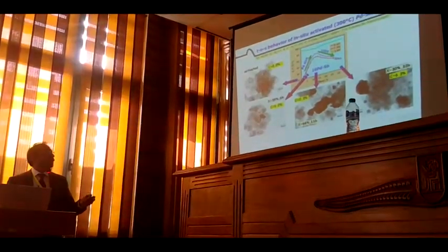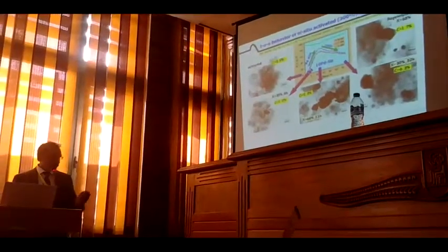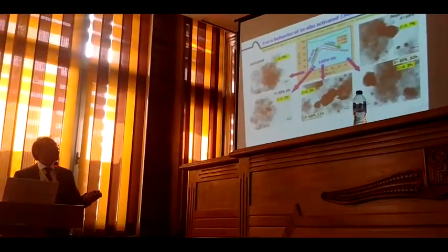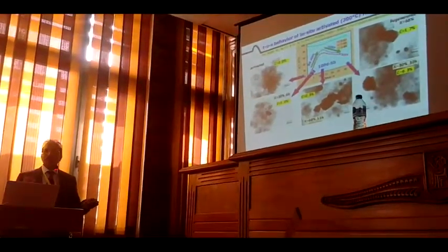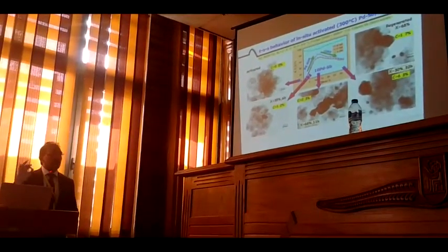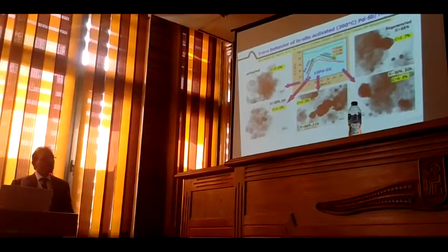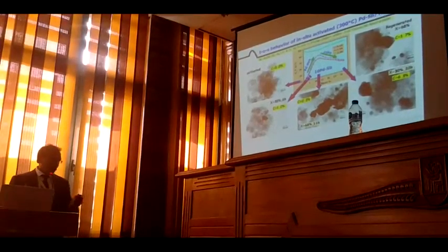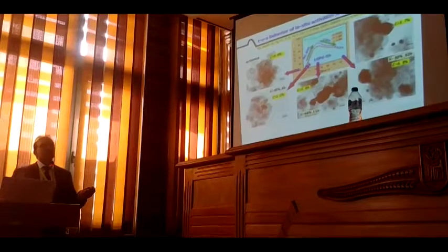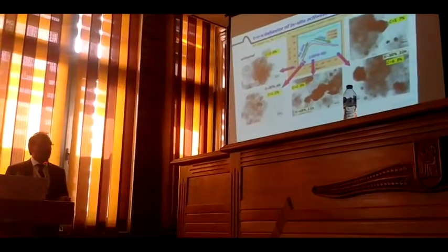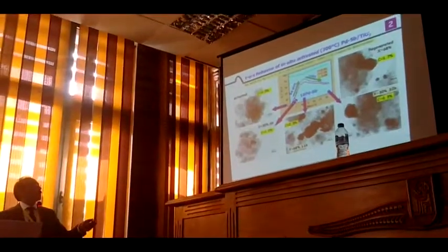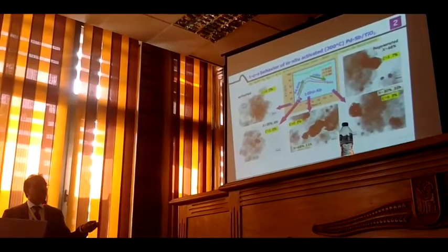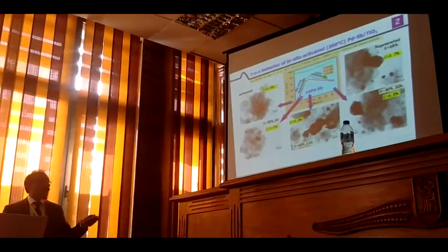So then we regenerated the catalyst. When you regenerate the catalyst, the coke is removed, the particle size remains the same or nearly the same. This means regeneration has no influence on the palladium particle size, but can only remove the coke. But we have not reached zero. There is still 1.7% coke at this attempt. And we have seen here already 2% coke has not that influence. So the catalyst can still work.